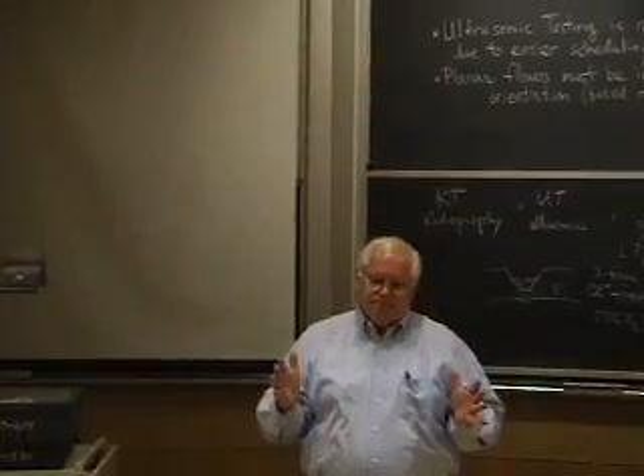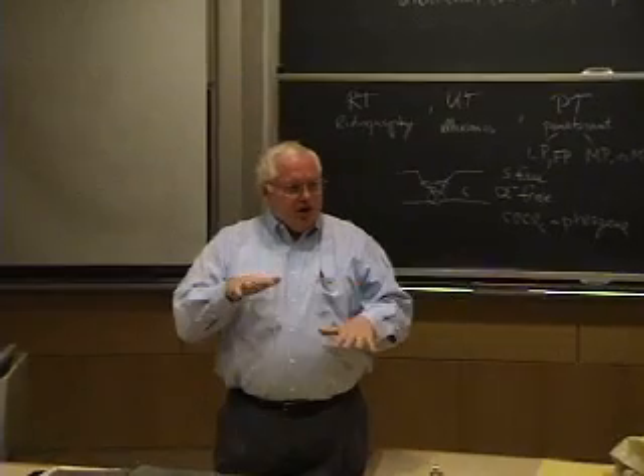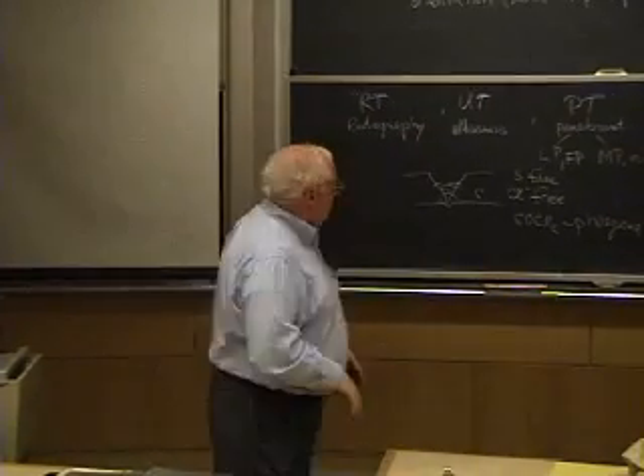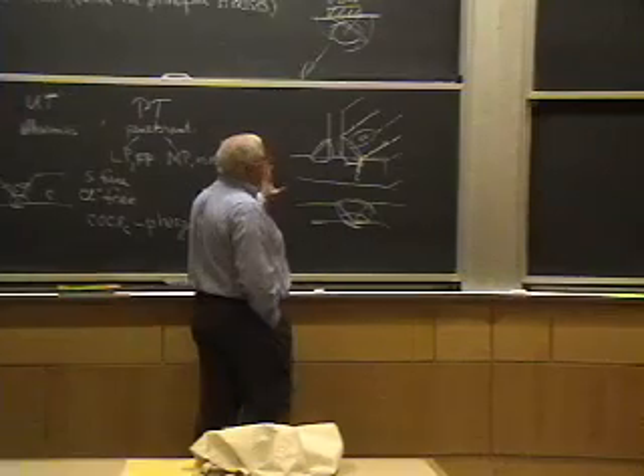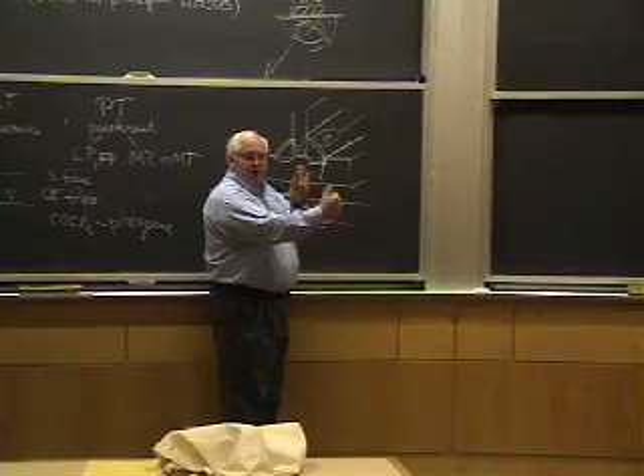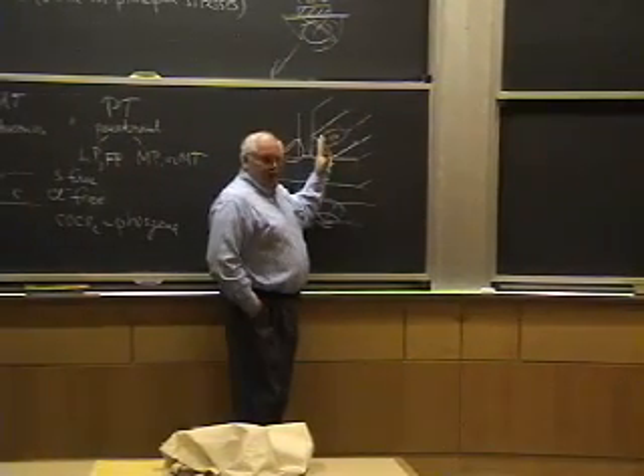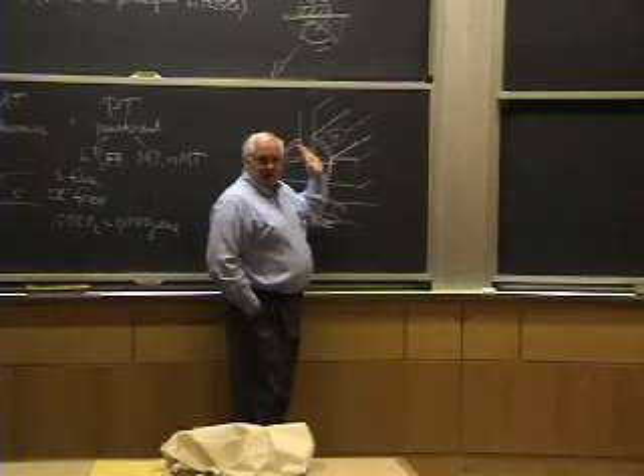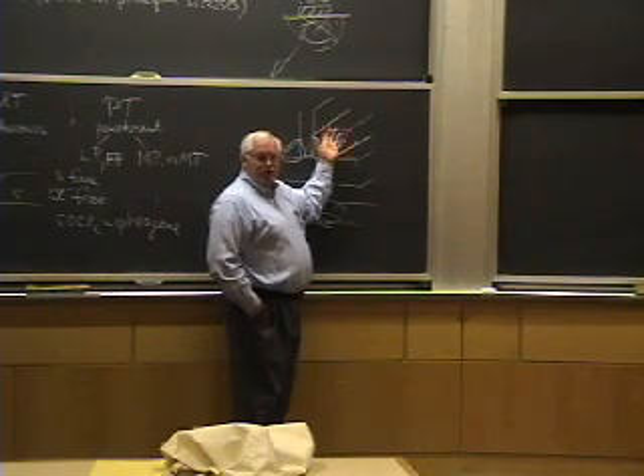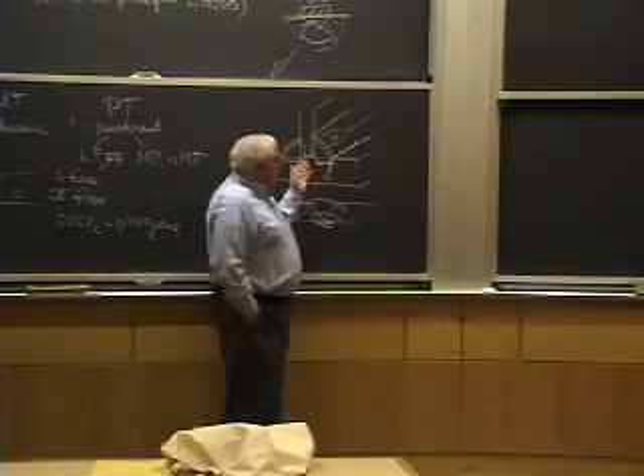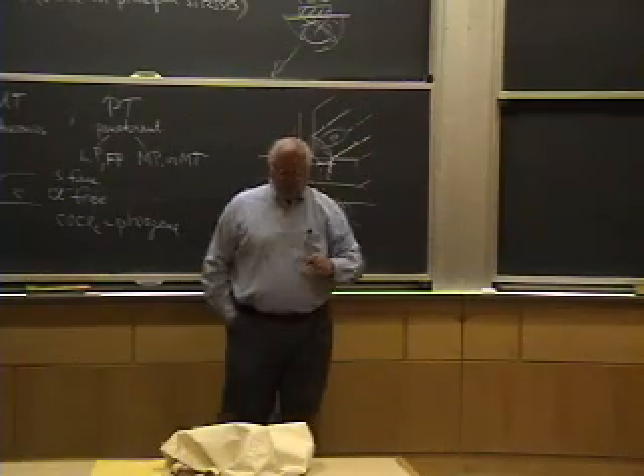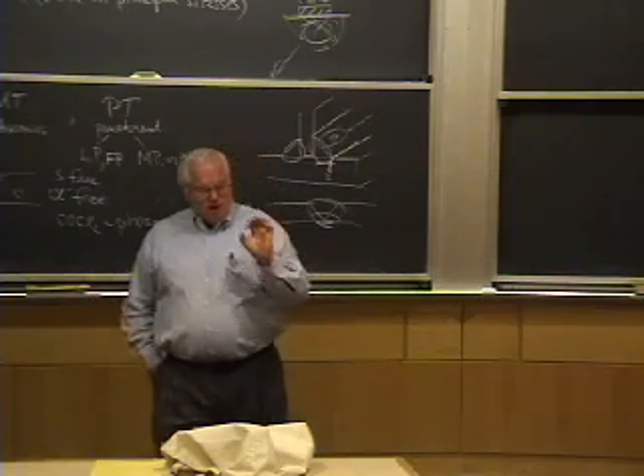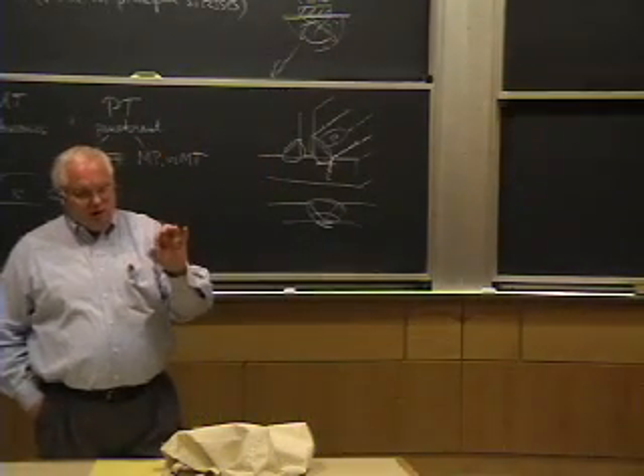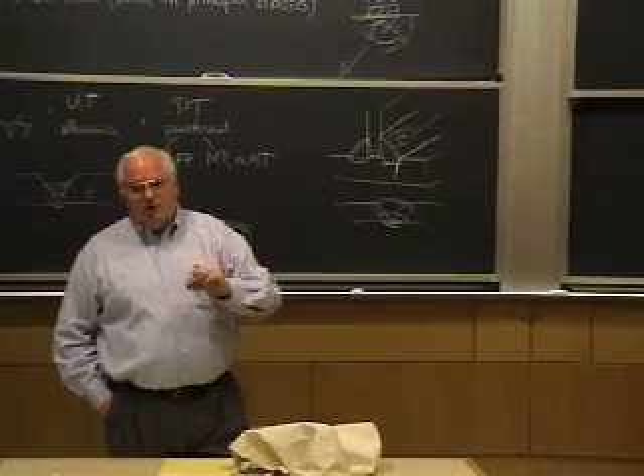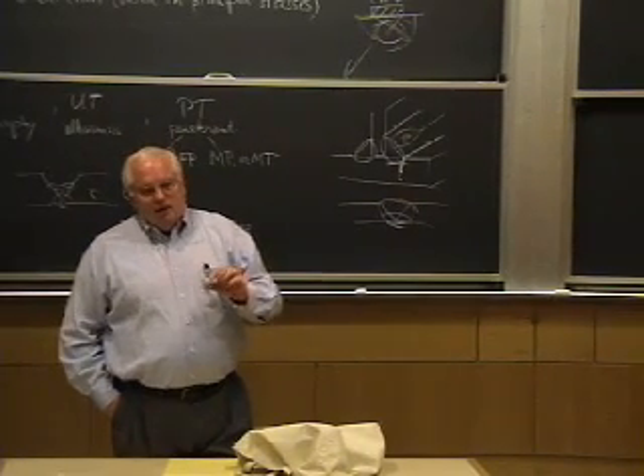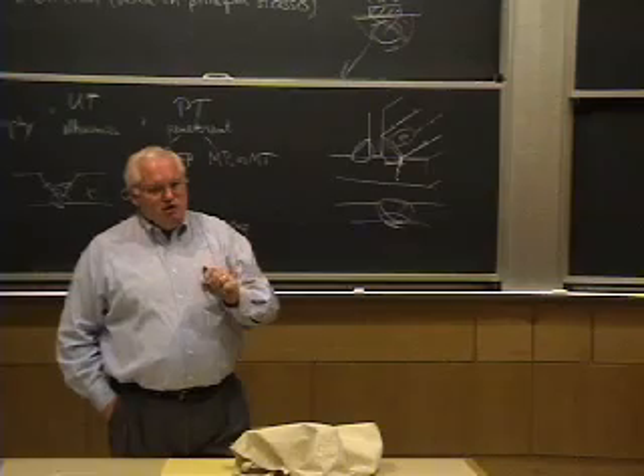Now, the problem with eddy current is it's very geometry dependent. So if I have some complex shape, if it's just a straight fillet weld that goes on to infinity here, but if I have an intersection at a corner of a fillet weld, well, the eddy current doesn't really know what to do. Because I'm going to have all kinds of magnetic changes and current variations as the geometry changes. But if I had something that's uniform in 2 dimensions, then I can probe along there. I have to often design a special eddy current probe, because these things have to be within less than a millimeter of the surface. So there's all kinds of problems with eddy current, but when you can use it, it can be very, very effective.